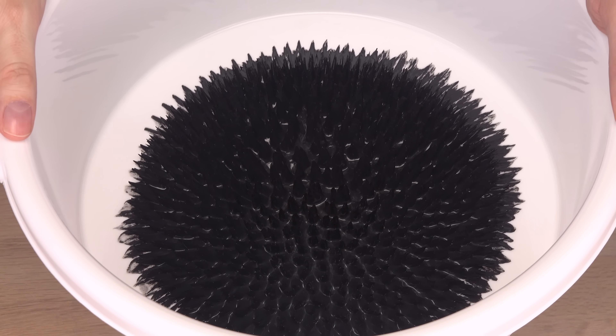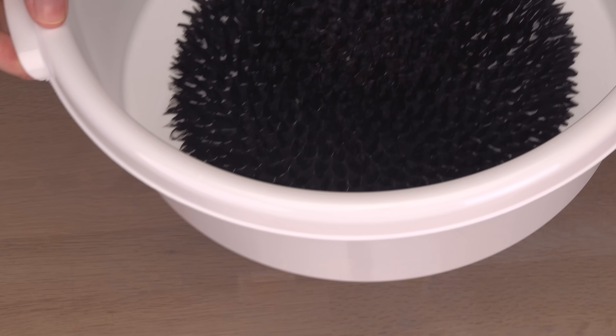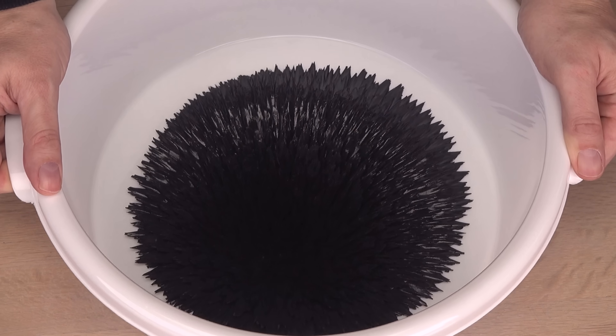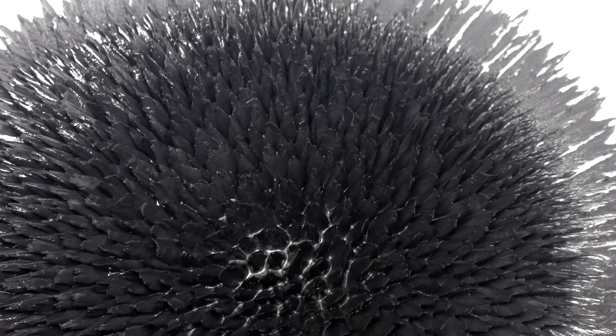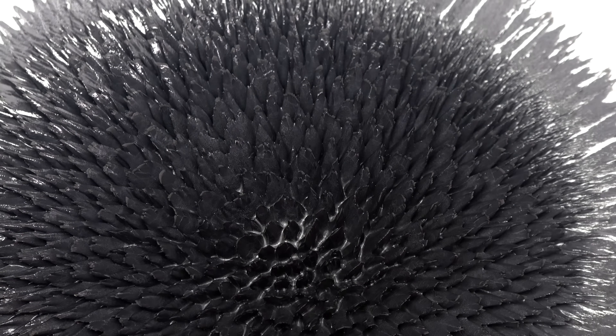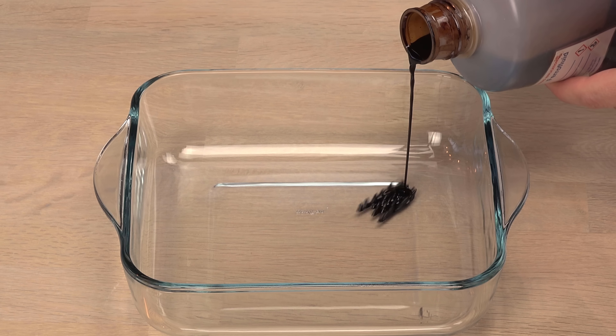Awesome! Most entertaining paint I've tried. Though it does have a strong tendency to form ridges and blades, not cone-shaped spikes. Likely due to the magnetic particles not being chemically encapsulated and therefore not able to move as freely in the magnetic field as in ferripaste and in particular ferrofluid.